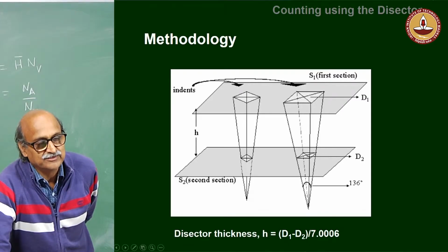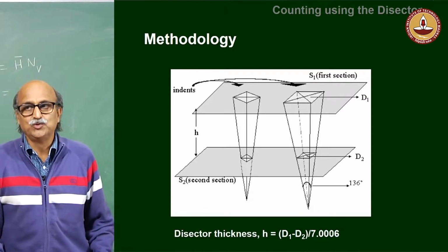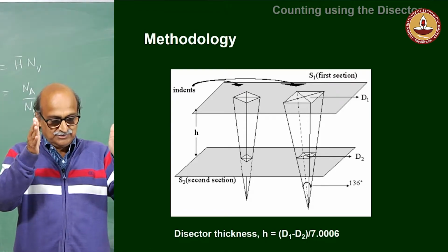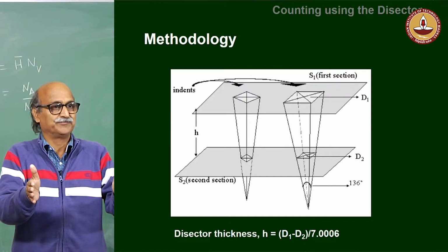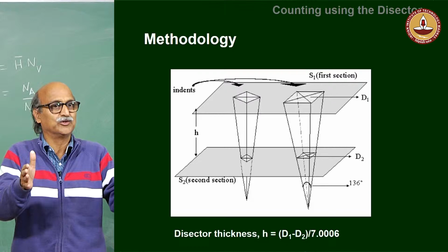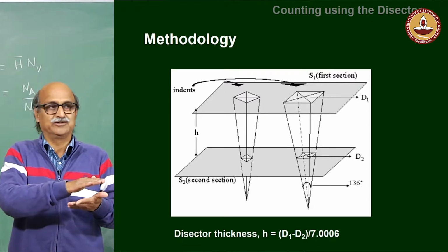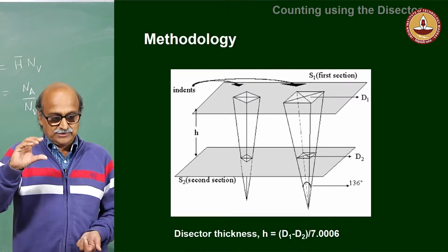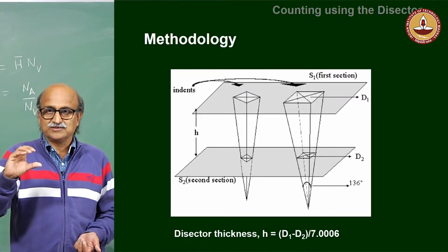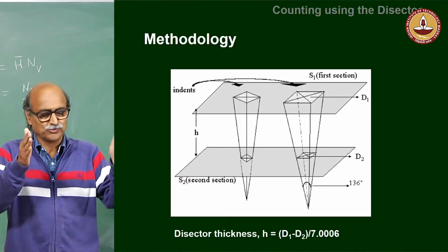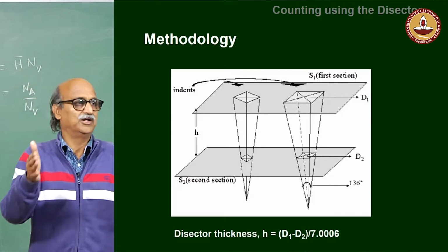Other thing that these indents are going to help you is, you want to observe the structure in the same area. So, if you put your indents properly, you can locate your area after removing the material. So, indents will give you the dissector thickness, and it will also enable you to locate your area, because you have to go back to the same area and do the count.